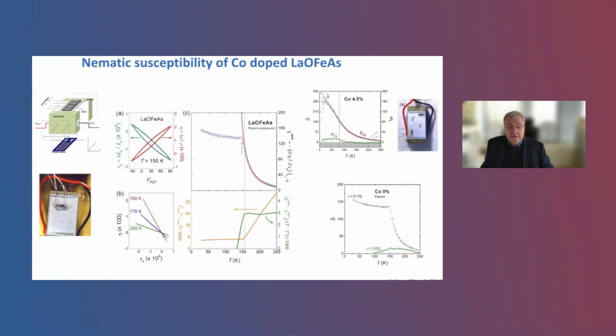If you plot the slope of these lines as a function of temperature, you derive this divergence of the nematic susceptibility, defined as the change of resistivity divided by strain. Okay, fine, no surprise. So we are approaching this nematic instability. You can fit this with the typical Curie-Weiss law, and that's shown here. This is not so bad.